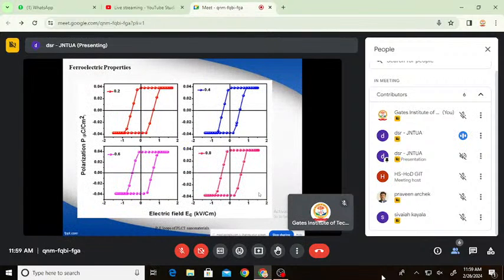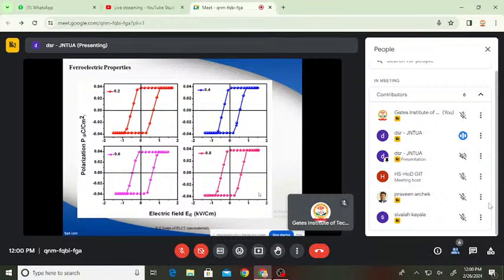Coming to the ferroelectric properties, the ferroelectric nature of the PLCT nanofibers as a function of lanthanum composition was studied here, using the plots of polarization against the applied electric field. It is understood that the PE loops of Z equals 0.2 to 0.8 contents exhibit well-defined hysteresis loops. Besides these hysteresis loops, they exhibited a distorted banana shape. It can normally create leakage current, which may be due to the oxygen vacancies formed on the upper surface of the grains instead of polarization.